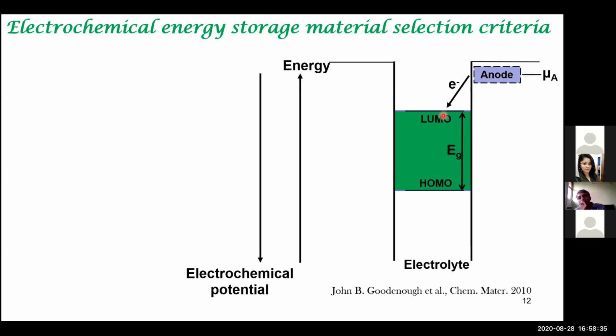Whenever there is such an electron transfer from the anode to the electrolyte, for example if it's an aqueous electrolyte, water decomposition can occur. You don't want that to happen. You want the electron transfer to happen only to the lithium ions, and not to the other chemical components of the electrolyte, which don't involve lithium. For example, in the lithium-ion battery in your cell phone, if I had water as an electrolyte, water would decompose into oxygen and hydrogen. You don't want that to occur.